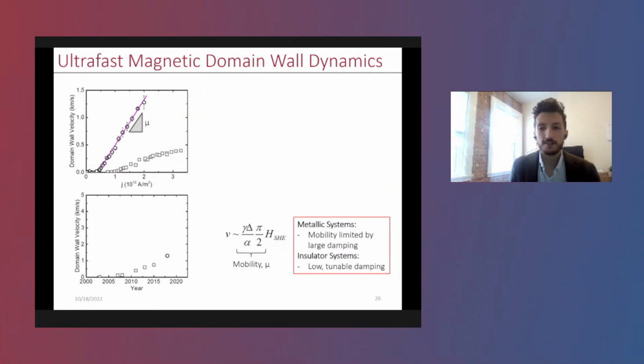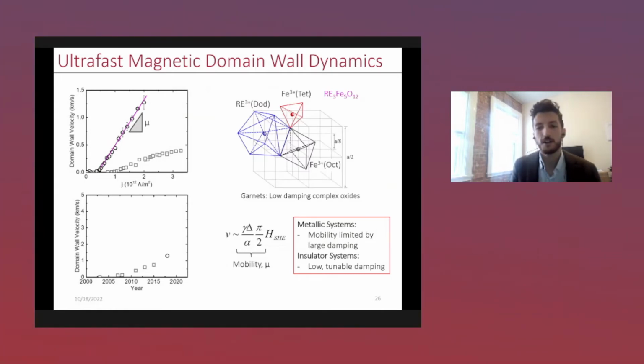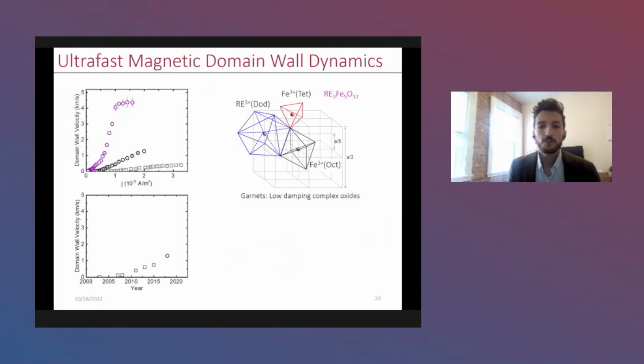And in fact, metallic systems, such as all the ones I've shown so far, the mobility is actually limited by the very large damping because of conduction electrons. However, there's a system that's quite more famous, garnet systems, which have already been introduced in this session, which are famous for not only their low damping, but also their tunable damping. And so what I'll show you is by engineering garnet hybrid metal oxide heterostructures correctly, not only can we drive domain wall dynamics much faster with higher mobilities, but this plateau that you actually see in domain wall velocity is not the same plateau that you saw for ferromagnets, but in fact, it's a fundamental limit, the relativistic limit of how fast the domain wall can move.